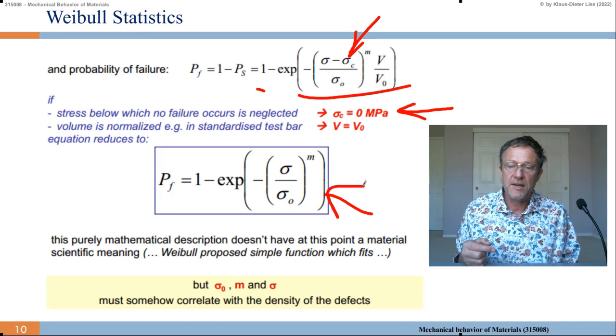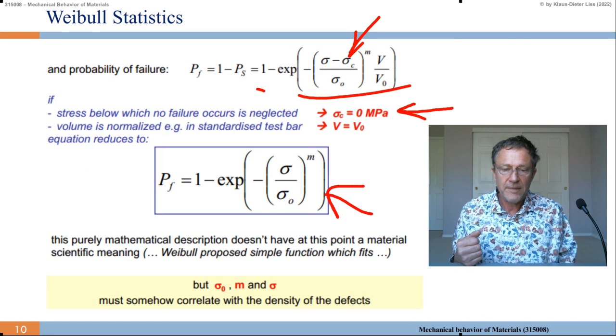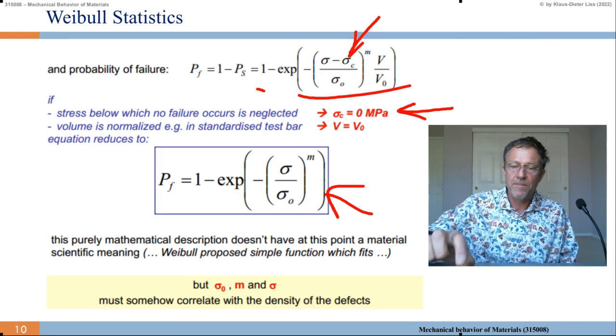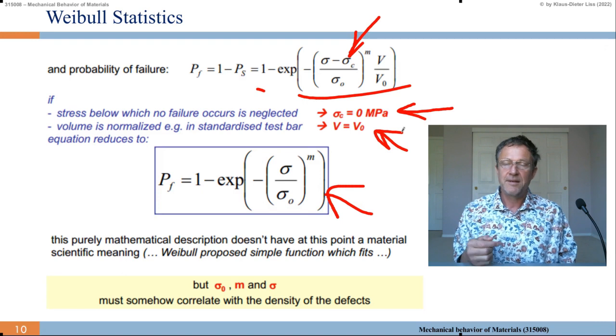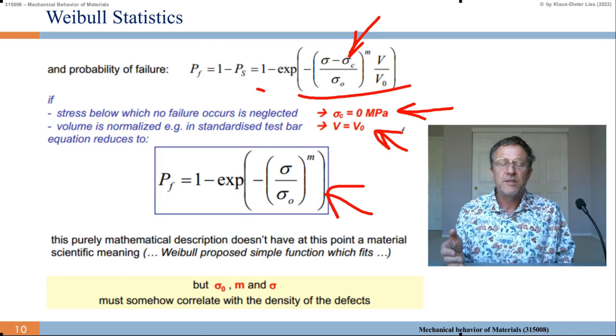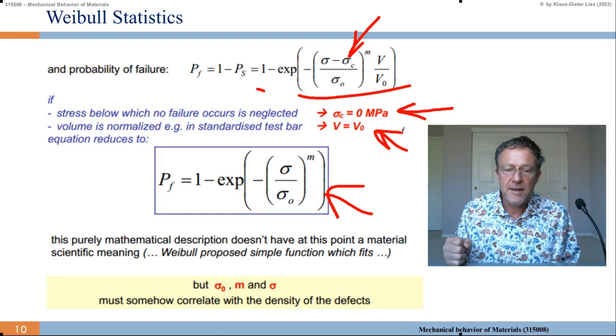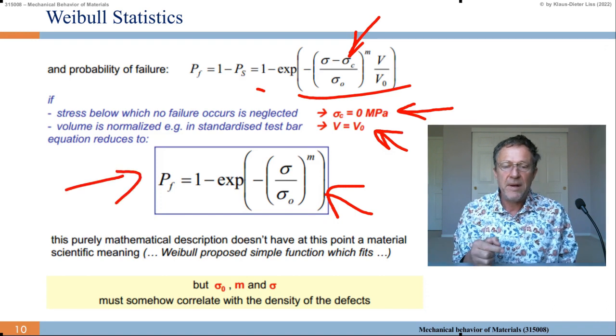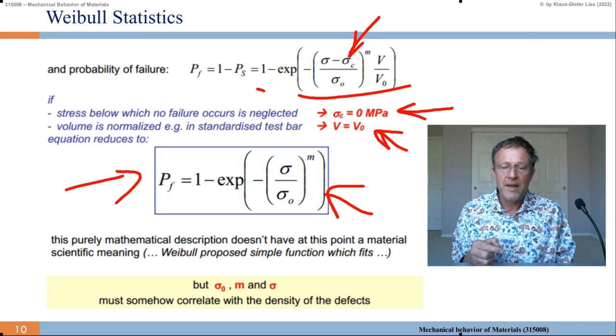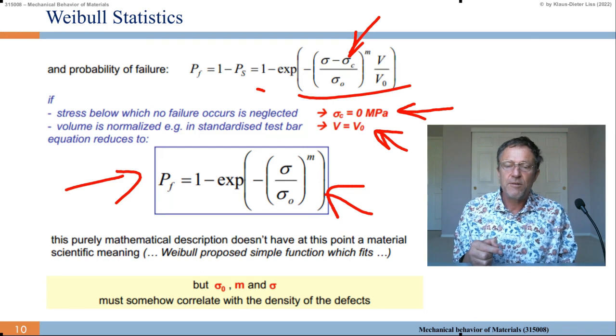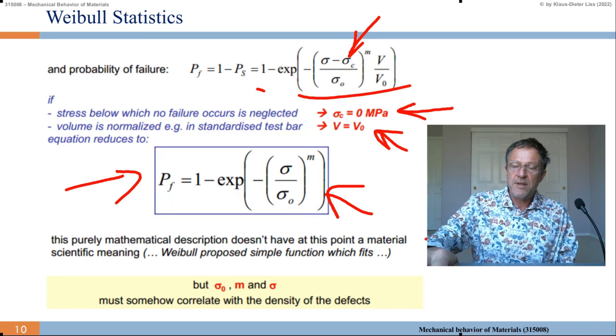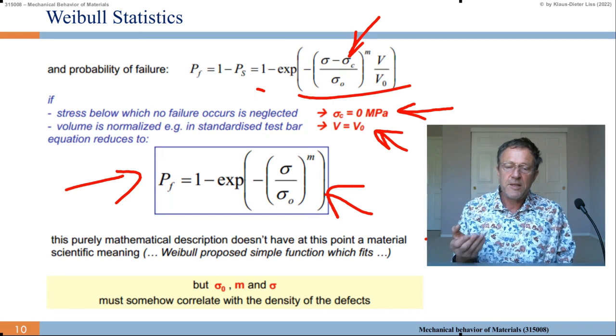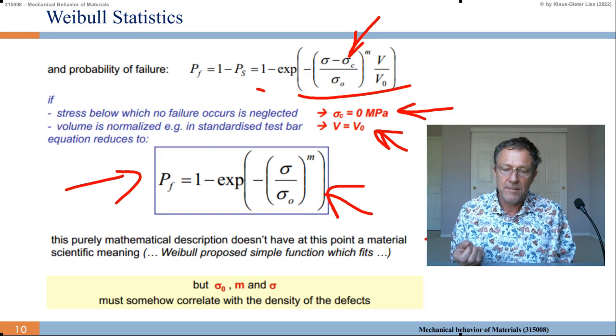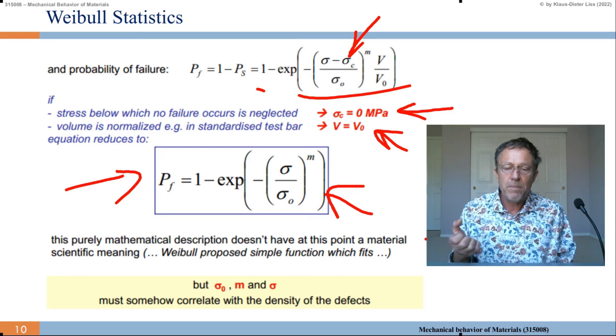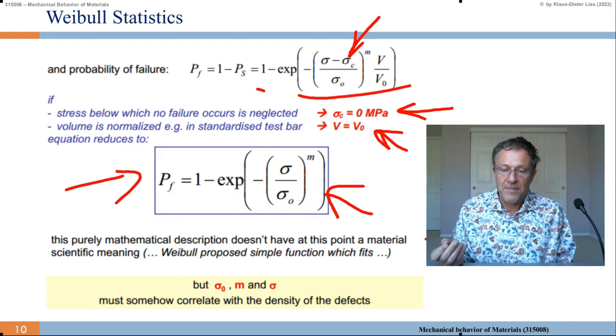Now the volume V is normalized. Let's make it V0. And in the standard experiment, as described by the societies, so engineering standards like ASTM, then PF, the probability of failure, becomes 1 minus exponential of minus sigma over sigma 0 to the m. Note, this is a pure mathematical description, and at this point doesn't have any material scientific meaning. Weibull just proposed a function which simply fits the behavior.